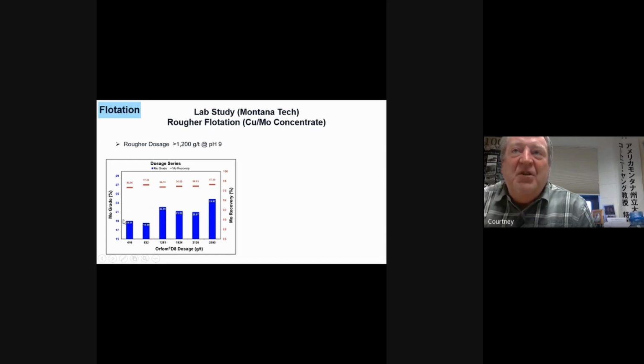Anything less than that doesn't work very well. Anything greater than that seemed to work okay. It's hard to tell if it actually goes down and then goes back up, or if this is kind of an average for this dosage, if you average these numbers. Point being is that you need to be greater than that for this Orfom D8 to work. Note that the recovery up here in the red numbers are really good for molybdenite. So good recoveries, better grade at the higher dosages. You really don't need to go higher than that dosage.